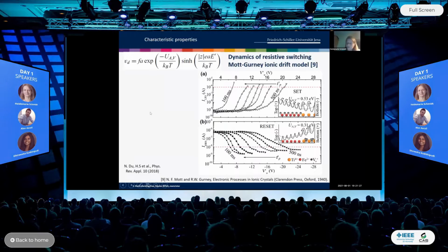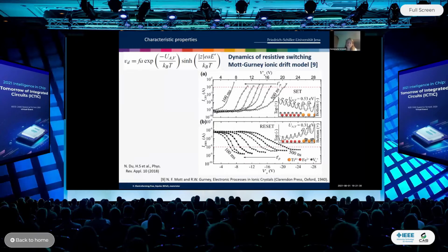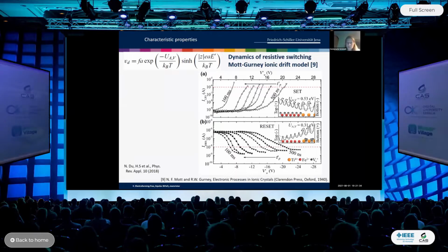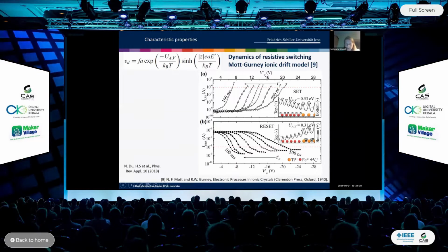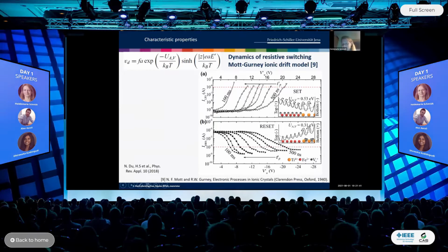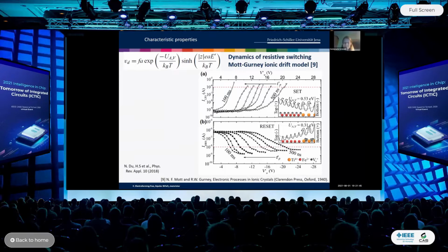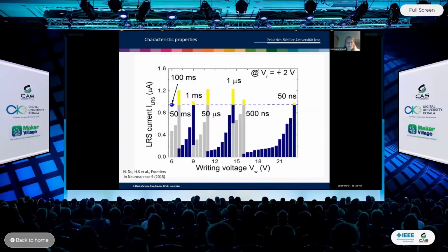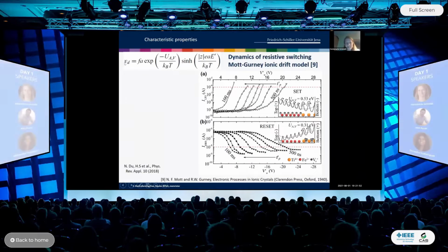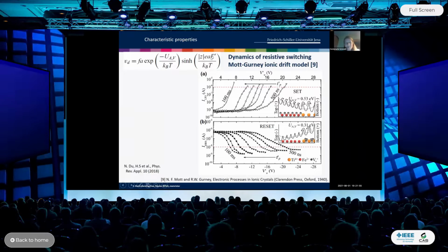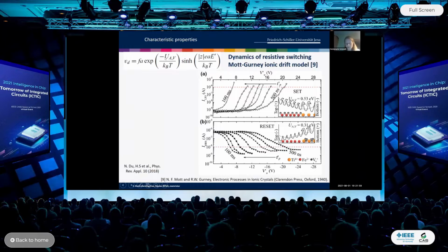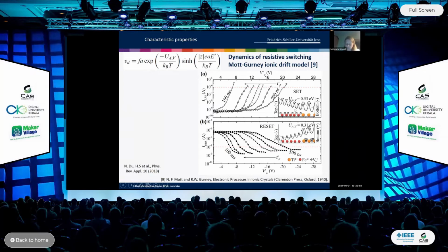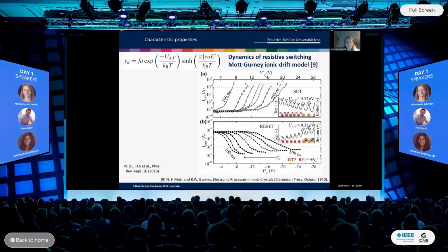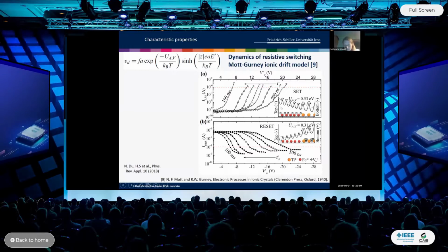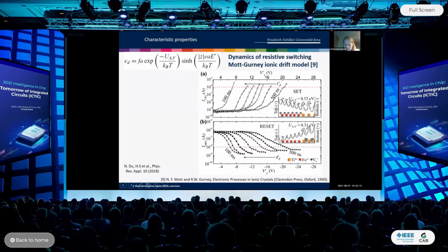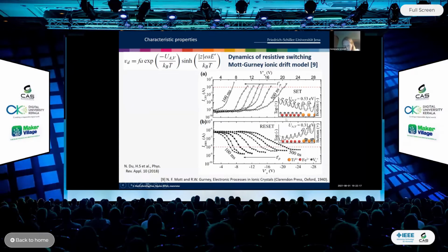Now comes the interesting point, which is really new and which we really investigated for those bismuth iron oxide memristors. There's a very old theory from 1940, much older than the theoretically predicted existence of the fourth passive device, the memristor, right? And this theory tells us how the drift velocity of ions depends on the electric field in the system, and also depends on a typical barrier height which has to be overcome by the ions in the crystal field potential of the host lattice. So what you see here on the sketch is a very much zoomed in sketch. You see the position of the top electrode, of the bottom electrode, and you see the oxygen vacancies.